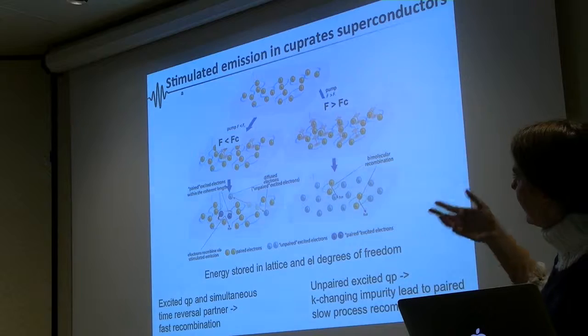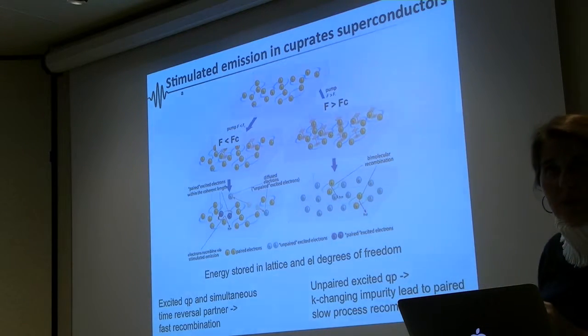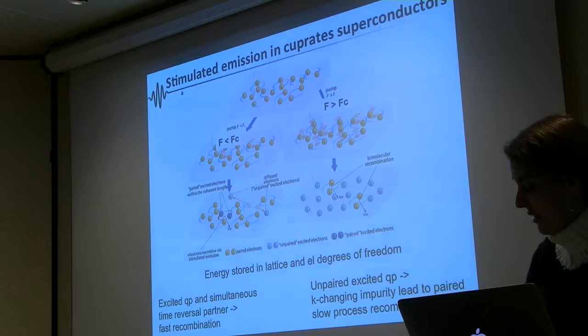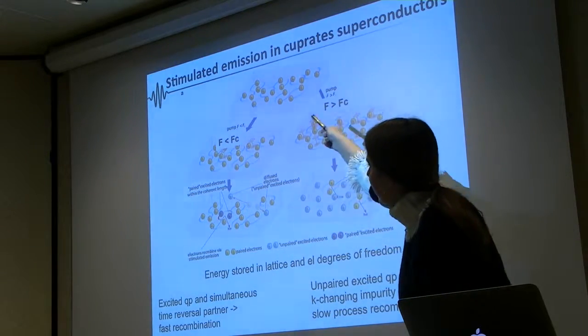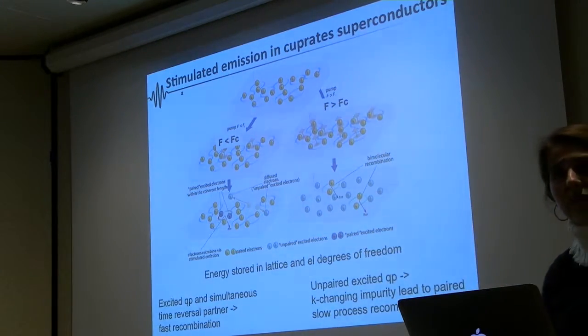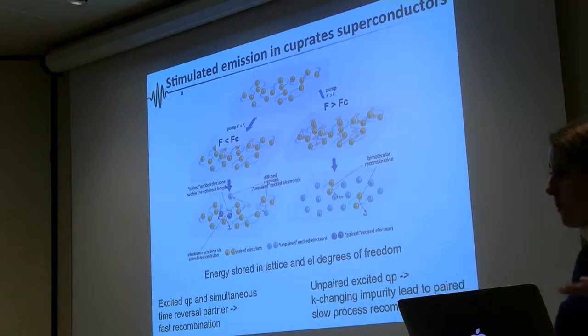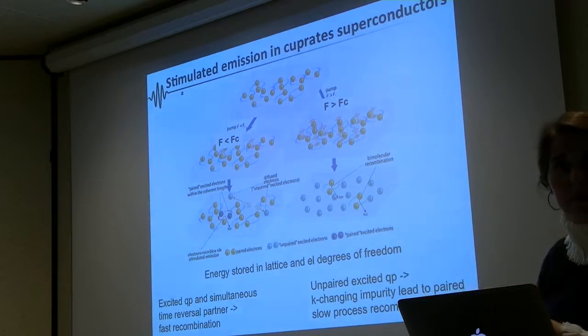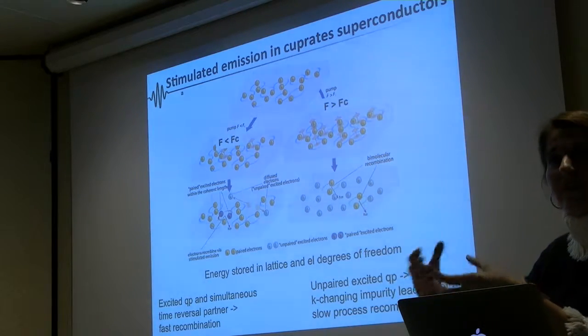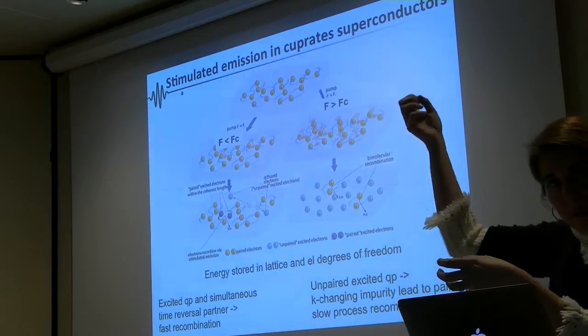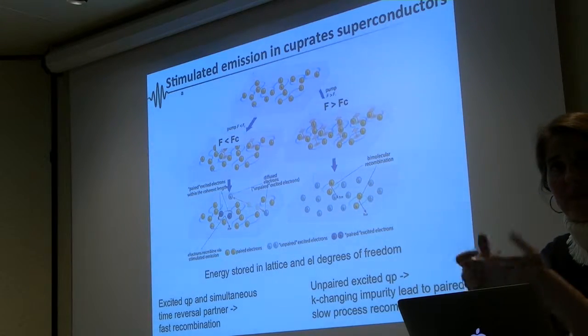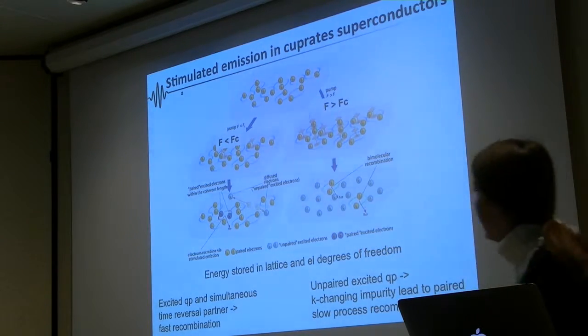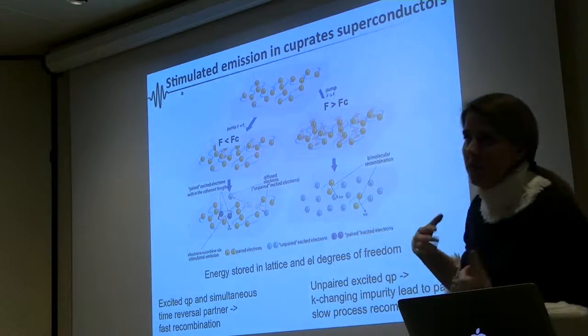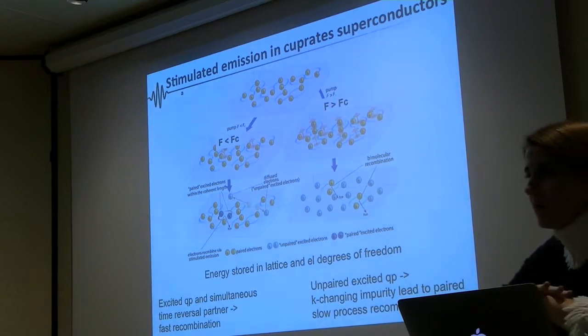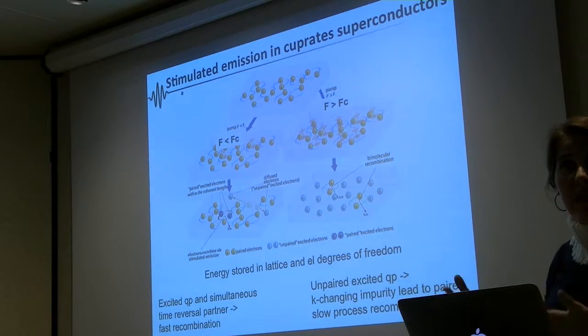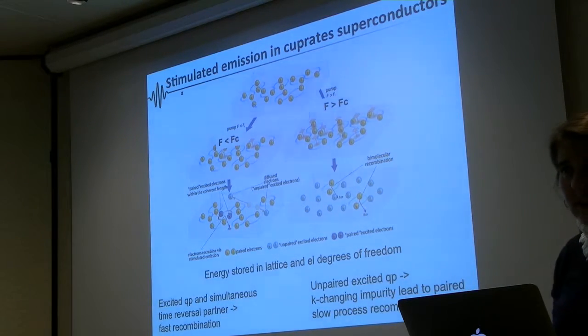The idea behind it is what he called the equivalent of a stimulated emission process. For the non-equilibrium quasi-particles, if you are in this low fluence regime, which means you still have a lot of Cooper pairs but you are partially breaking them, there is a much higher probability that the energy stored in the lattice goes back to recombine pairs, and this phenomenon is like a stimulated emission process. If you are in this other regime, where the fluence is much bigger than the critical fluence, you have pretty much killed all the Cooper pairs, and then this type of recombination process doesn't take place.